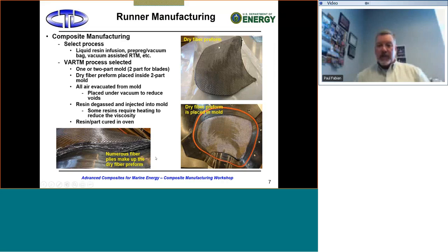And so this just shows the dry fiber preform. Just for reference, these blades are nominally about 18 inches across in the longest section and probably about 14 inches deep across the height of the blade. Down here in the root section, the thickness is a little bit over an inch, and that comes down to about a 1/4 inch thick at the tips. And so the layup and actually all the plies and making sure that you get the right fiber volume fraction within the part and maintain the thickness, that's involved and takes a lot of engineering to do that, but it's certainly not beyond the capabilities of most places.